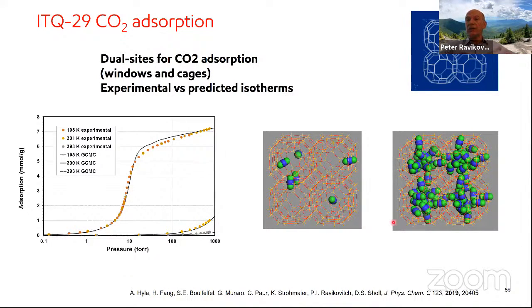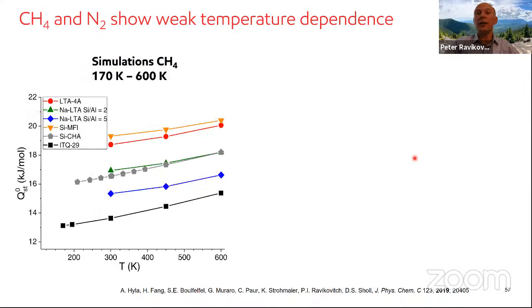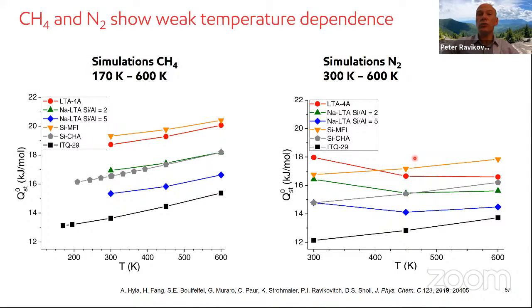And what simulations show is that ITQ29 has two types of sites. You have window sites, and CO2 adsorbs at low loadings in these window sites. And then there is the rest. So there is a redistribution of molecules between the window sites and the rest of the sites within the LTA cage of ITQ29, and this redistribution gives rise to the temperature dependence of the heat of adsorption. Methane and nitrogen show rather weak temperature dependence, which is much more commonly observed in the literature.